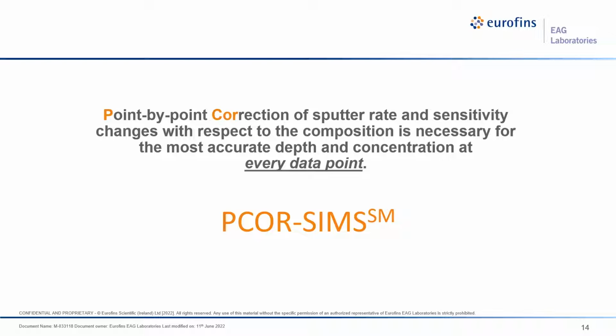PCOR-SIMS, that is point-by-point corrected SIMS, addresses these problems by employing empirically derived analytical functions to correct for the SIMS matrix effects as they come into play when one deals with materials that are dissimilar in nature. These corrections can be made for group 3 elements, dopants, and impurities alike. And the changes with respect to composition occur on a point-by-point basis. That is, for every impurity or dopant data point, the matrix composition is determined and the corrections are made according to the measured composition at that data point.